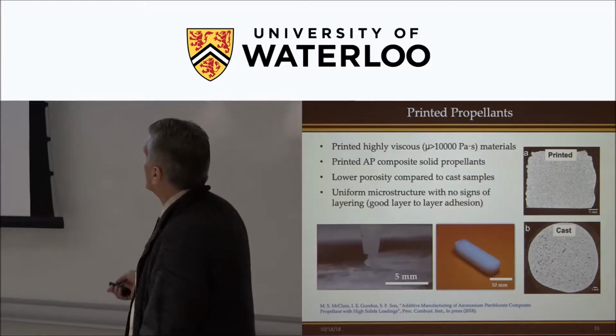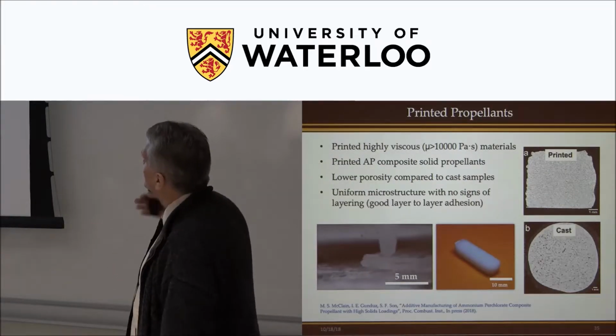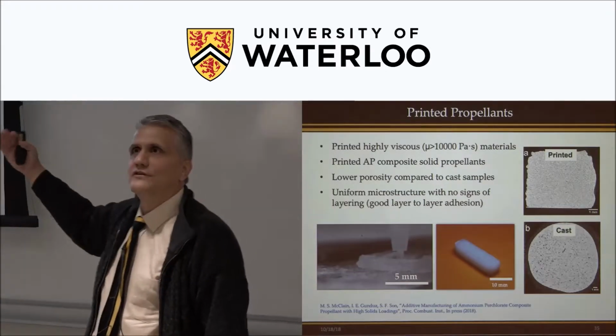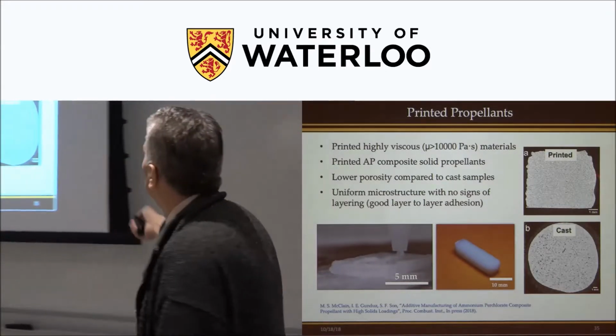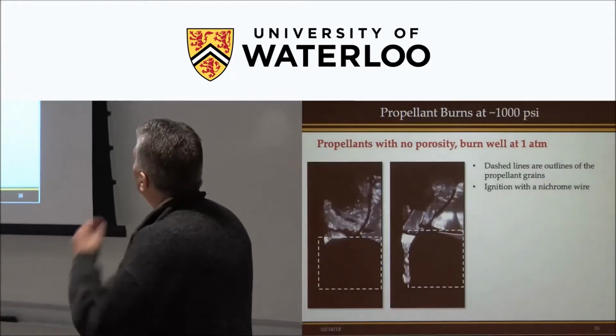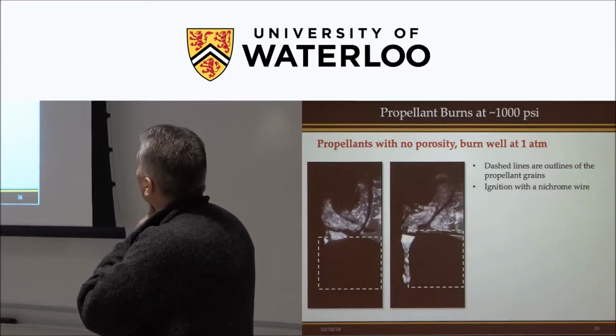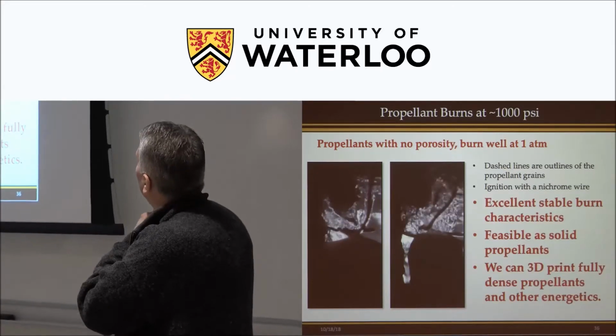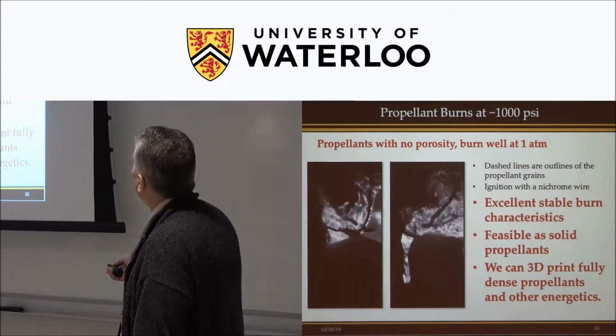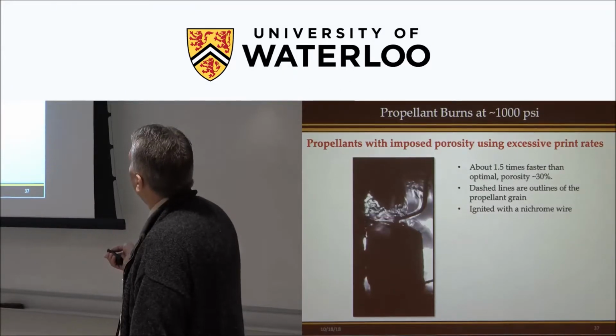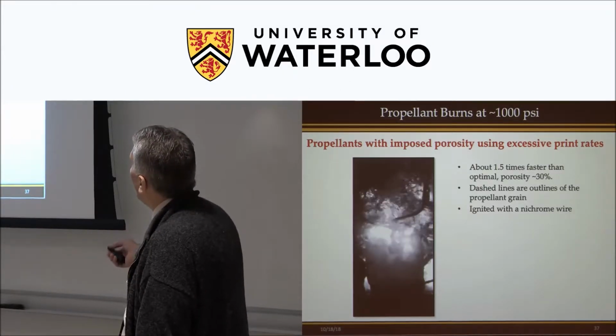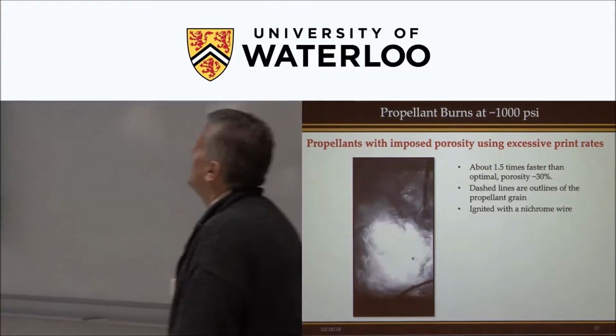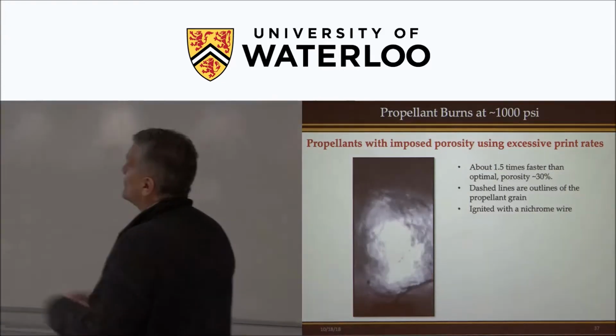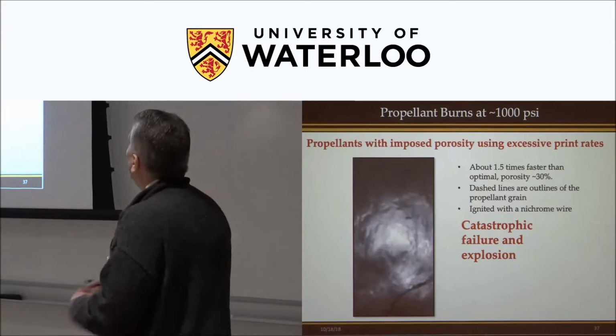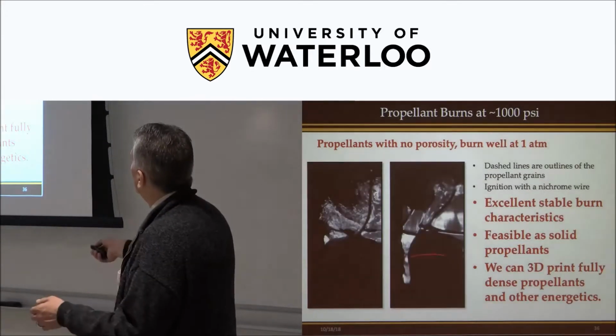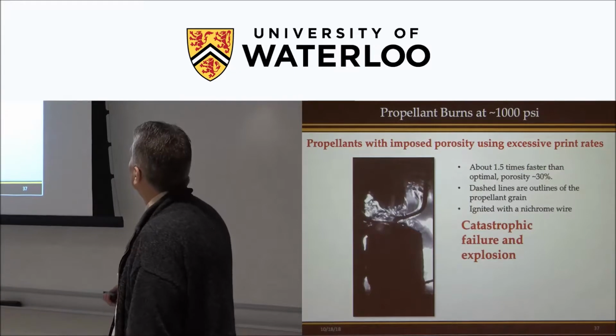But these are very nice, and what I would consider very nice is I can take that propellant up to pressure and it doesn't explode, because there are very few voids there. So this is burned at 1 atmosphere. 1 atmosphere is relatively easy to work well. But at pressure, importantly, it burns well. If we add porosity, though, we can make that strand explode. So we can introduce porosity if we want, or have cases that even at pressure burn in a normal fashion, as you would like.